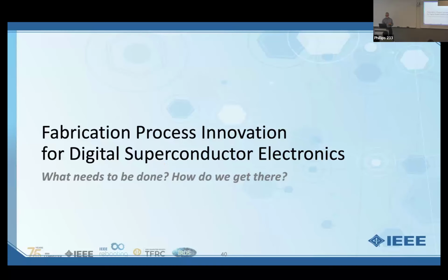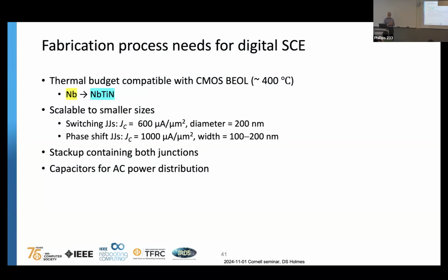I'm going to talk a little bit about the fabrication process. So what do we need? We could look at all of this stuff and ask, what do we need? One thing is we need a thermal budget compatible with CMOS back end of the line. With CMOS wiring layers, all that kind of thing, you can use up to 400 degrees Celsius roughly. Right now, we don't have that. We have a much lower back end of the line. Our processing temperatures have to be kept lower, and so we cannot take advantage of all of the things that have been developed for CMOS, for gap fills and everything else. That needs to change.